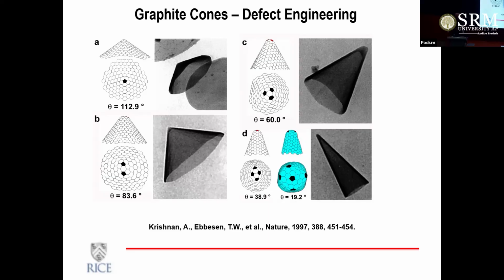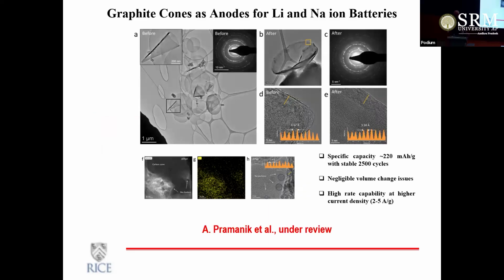But recently, when we were looking at various types of carbons for sodium-ion batteries, because you need these hard carbons, the graphitic carbon doesn't really help. This particular structure seems to work extremely well, because one of the problems with the hard carbons, which have carbon plus other heterogeneous elements, is the cycling stability, right? Because there are reactions occurring at these sites where there are non-carbons. But these graphitic cones, they are pure carbons, but their morphologies are different, and they seem to work extremely well for the sodium intercalation and deintercalation. So again, having these engineered defects in structures could give you opportunities to explore interesting applications like energy storage.